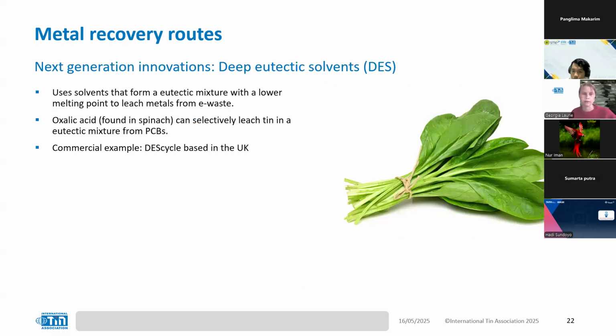If we look at some next generation innovations being explored to recover tin from e-waste, deep eutectic solvents are an example. They are a mixture of solvents that form a eutectic mixture with a lower melting point than any of the individual solvents. This is great because it tends to use greener and less toxic solvents, but it also means we can melt that mixture at a lower temperature, so we don't have to use temperatures as high. And we can tune these mixtures by altering ratios and concentrations to alter their properties, depending on our target metal, for example. This method is being trialed not only in academic literature, but commercially.